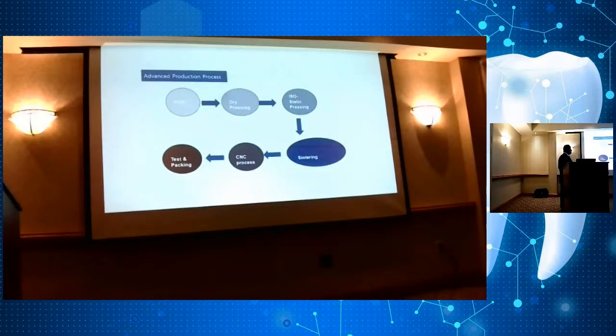So this is just a schematic of how we do things at ADITE. Research and development, which is part of my deal, the dry pressing, and then the isostatic pressing. Please understand that this is a more expensive way of making zirconia. The dry pressing is the uniaxial pressing. Then you transfer it, encase it in a polyurethane material in a vacuum. Then it's immersed in a liquid medium, and 20 tons of pressure is applied during the isostatic state. What this does is it creates a very even, homogeneous density. When pressure is applied from all different sides or points, you have a material that is extremely uniform in density. You don't find this with uniaxial pressing or the colloidal emulsion process. That is the big advantage to isostatic pressing.